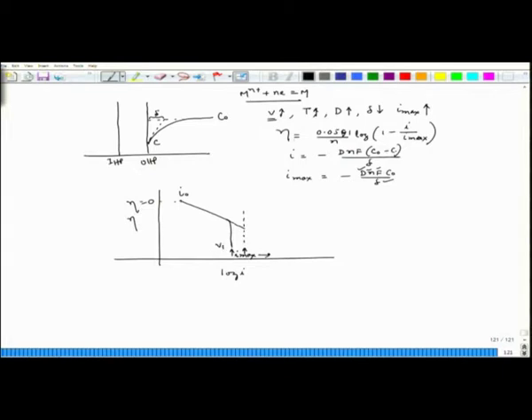So now in this case it is velocity 1 and in this case it is velocity 2, and V2 is greater than velocity 1. So I max increases, and that is why this curve is switching to the new position, which is this one. Now, if your velocity increases further, I max will again switch to the right. Then we will have another new position of I max. Let us say this is my I max when V3, and V3 is greater than V1 as well as V2. So this activation polarization part would still increase further. Interestingly, as we are increasing velocity, because of these factors we are increasing I max, and that is why the polarization curve is shifting towards the right. That means the appearance of I max is shifting towards the right. This situation will have a strong effect on corrosion of metal.